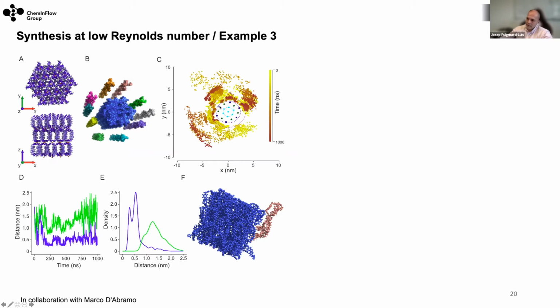What you see there, these blue dots, are the vertex of the hexagon, and then the green is the face. This is a density map, because what we did was put these 10 strands, let the system evolve, and see which of these 10 strands would react first. And what you clearly see in this density map is that they tend to react first from the vertices. This is in fact what we were observing experimentally. And this is very clear here: the blue ones are seeing these strands around them faster. So this allows us to prove that what we were observing experimentally was in accordance with theory.